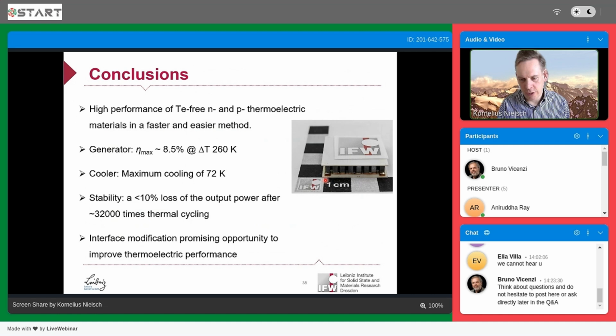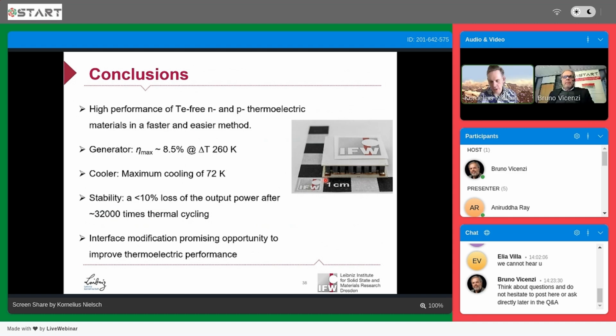So I've shown that we have developed very high-performing tellurium-free thermoelectric materials by a quasi-fast and very scalable technique, mechanical alloying. In terms of the thermoelectric generator, we obtained an efficiency of 8.5%. Maximum cooling temperature was 72 Kelvin. The stability is extremely promising when we do the encapsulation by hafnium oxide in our modules. And we are currently working further on this interface modification of our modules.